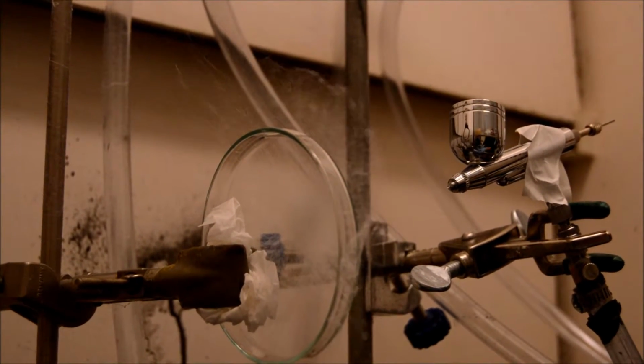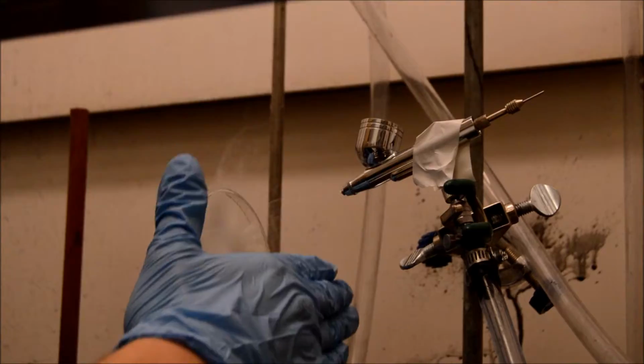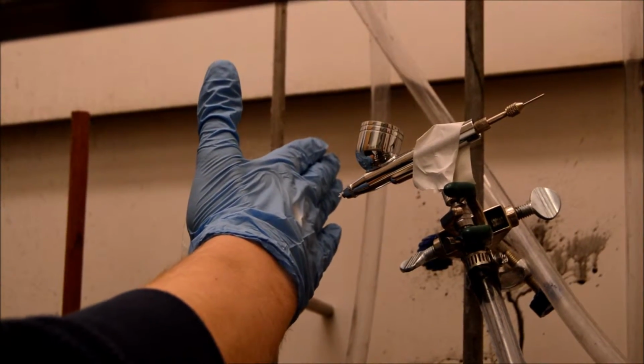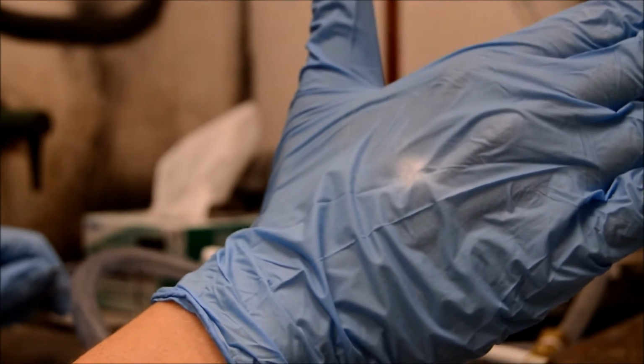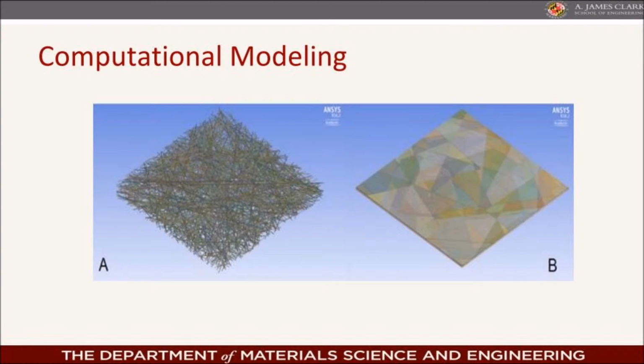These fibers stack to rapidly form a non-woven mat on nearly any substrate. The mats have high porosity and an interconnected pore structure, both extremely favorable properties for filter membranes. To learn more about our system, we use the software tool ANSYS to simulate the generation of nanofibrous mats. From studying the resulting models, we found a direct relationship between the nanofiber diameter and the effective pore size of the filter, something that had also been observed in literature. Although we have not fit our computer model with our experimental data, our research suggests that mats composed of 100 to 300 nanometer fibers will form pores in the microfiltration regime.